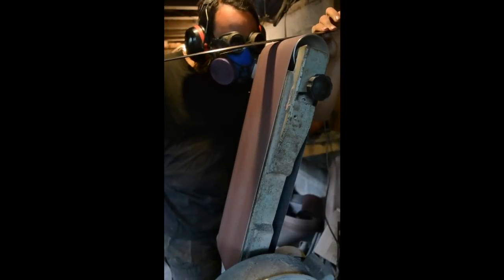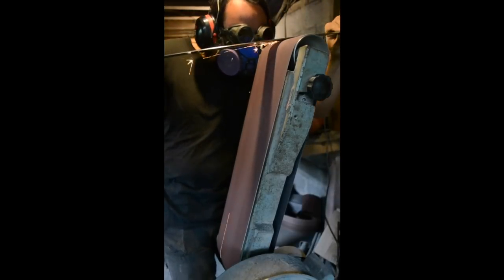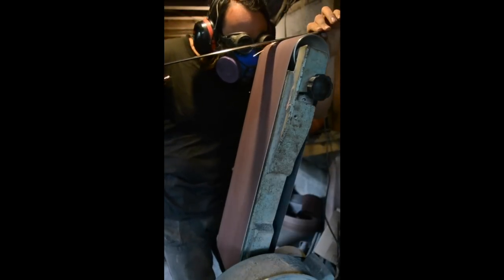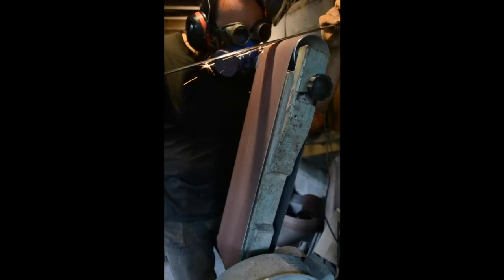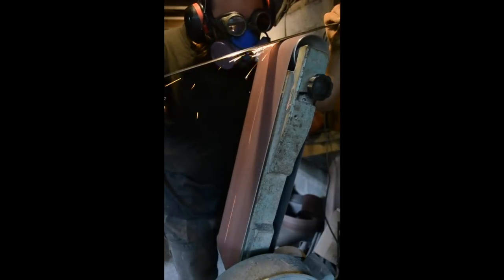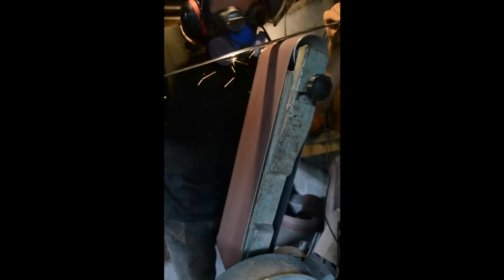As things stood, I had to go back to the grinder, mess up my nice polish, and remove some material. It was also more difficult than if I had done it during the initial grinding. Because the material has been heat treated, it's much harder to remove material. I also can't let it get too hot or I risk wrecking the heat treat.